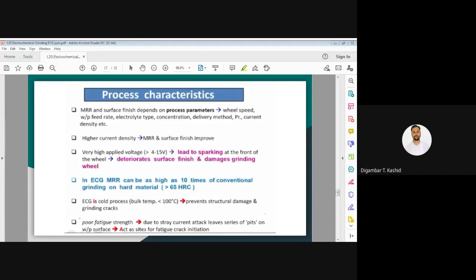Then another process characteristic is that in case of electrochemical grinding, the material removal rate can be as high as 10 times greater than your conventional grinding on hard material. You will get this on hard material having more than 65 HRC. Again, that is 10 times more than your conventional machining for a hard material workpiece of 65 HRC. Okay, so it is a cold process.